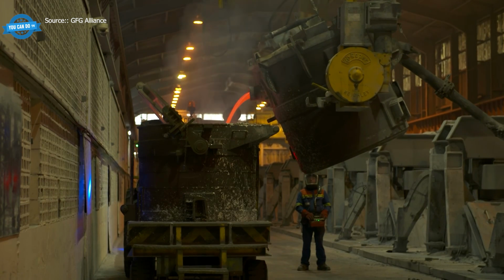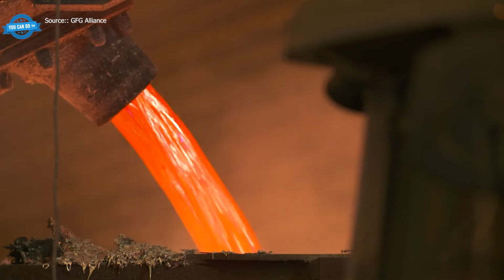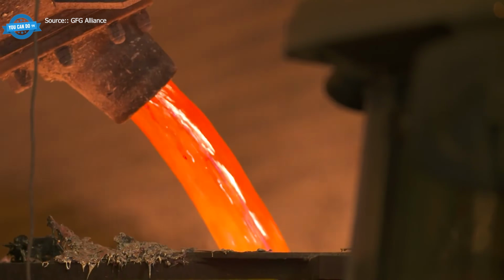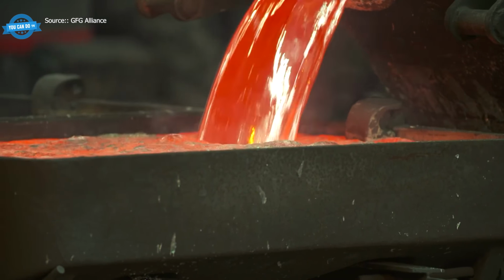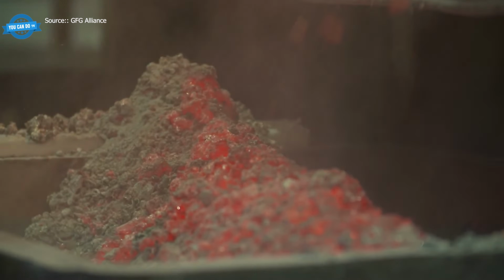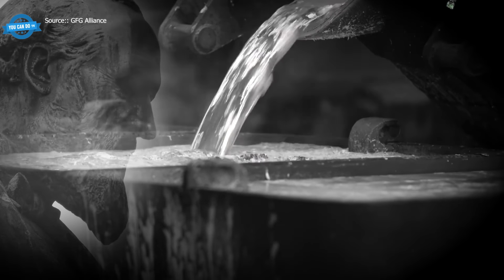Primary aluminum smelters are strange places, because they need almost as much electrical infrastructure as an entire city. A typical smelter runs pot rooms visible from space, with rows of electrolysis cells drawing enormous currents through a bath of molten cryolite and dissolved alumina. Pure aluminum sinks to the bottom of the cell and gets siphoned off periodically. Carbon anodes are consumed in the reaction and replaced regularly.